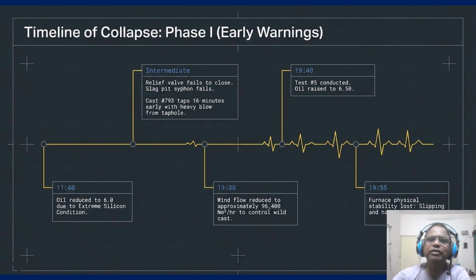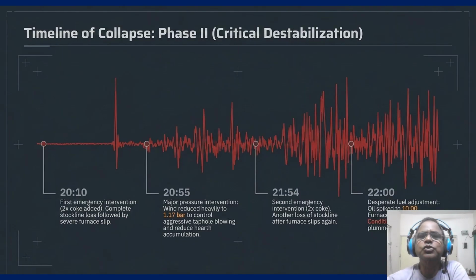Coming to the timeline of collapse, that is phase number 2. This is what a dying furnace looks like on a monitor. At 20:10, they tried a first emergency intervention by adding a double coke charge, complete stockline loss followed by severe furnace slip. By 2055 rather, wind was slashed again to 1.17 bar at 2200. In a state of total desperation, the injectant was spiked to 10.0, but it was too late. Hot metal was already plummeting to 1340 degrees centigrade.